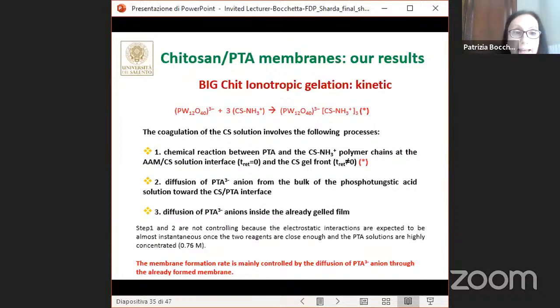So in order to evidence the kinetically controlling phenomenon, we analyzed the different processes involved in the ionotropic gelation of chitosan. The electrostatic chemical reaction is expected to be very quick and not controlling. The second process is the transport of phosphotungstate anions from the bulk of the phosphotungstic acid solution toward the alumina-film interface, and also this is a very quick process and not controlling. Finally, we have the transport of phosphotungstate anions inside the already gelled film. So we can hypothesize that the gel formation rate is mainly controlled by the diffusion rate of the phosphotungstate anions through the already gelled chitosan layer.